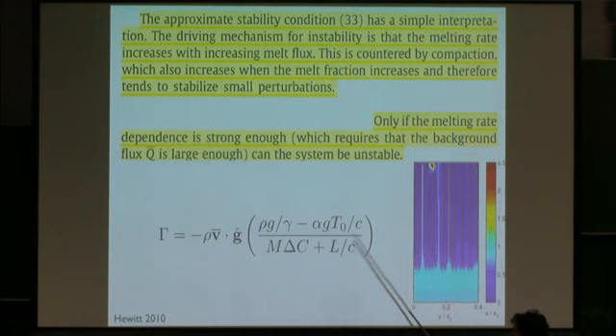So really, it's the latent heat penalty that you're paying, and that is limiting the amount of melting that can take place in a channel. If you melt too fast, the temperature goes down, you reduce the melting rate. So this is an important part of this channelized flow question. To channelize flow, you have to overcome the energetic cost of melting, and that was left out of early models.